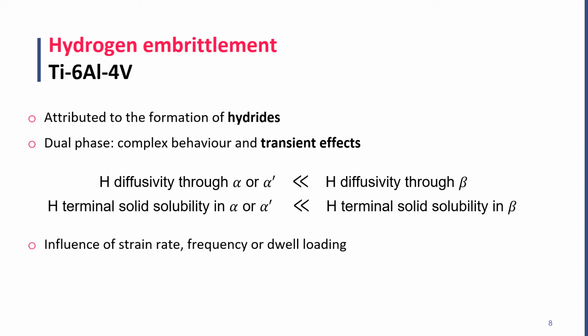very brittle phase. In titanium-64, which is an alpha-beta alloy, as you probably know, hydrogen transport and hydride formation is more complex. Alpha phase and alpha prime, which is the martensite that is usually formed during SLM, are hexagonal close-packed phases and have lower diffusivity and lower terminal solid solubility than the beta phase, which is a body-centered cubic crystal. And so the presence of martensite will in principle delay hydrogen diffusion, but increase hydride formation. We must also take into account that embrittlement is strongly influenced by hydrogen kinetics, especially during cyclic loading, such as the case of cold dwell fatigue.